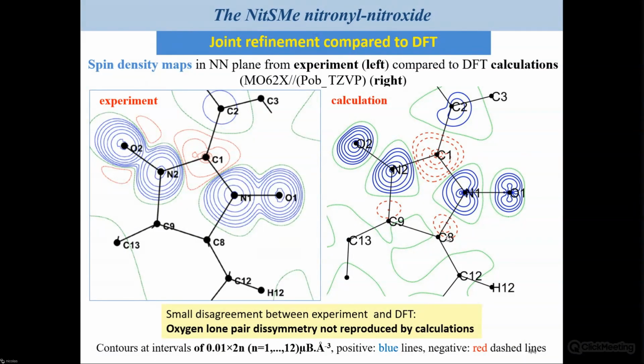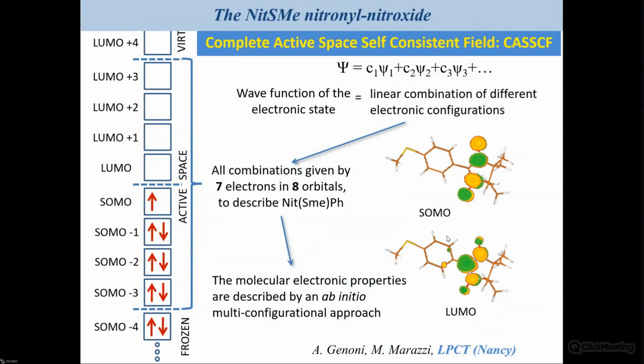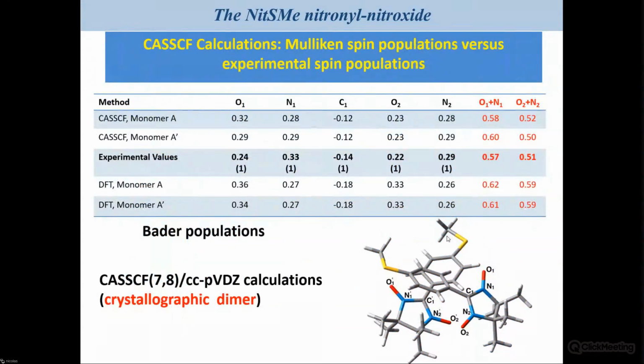kind of function. So our idea was to not use DFT calculation, but to use CASSCF calculation, because in principle, it should be more sensitive to that very tiny effect. And that works. That calculation has been made in collaboration with Alessandro Genoni and Marco Marazzi, at that time at the LPCT at Nancy. And the results were very interesting. Of course, for that calculation, we consider the two interacting radicals. We call that a dimer.